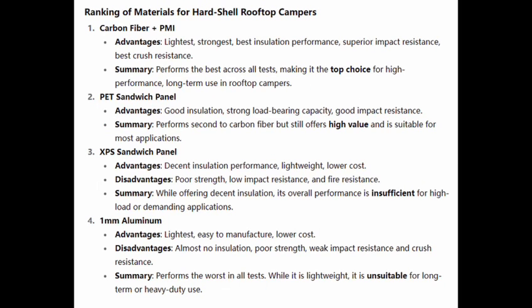Final ranking of the 4 materials. First, carbon fiber PMI sandwich panel. Second, epoxy resin PET sandwich panel. Third, unsaturated resin XPS sandwich panel. Fourth, aluminum. This test is a simplified comparison, and the results are limited by the test conditions, not representing all situations. Please excuse any shortcomings, and we welcome your valuable feedback.